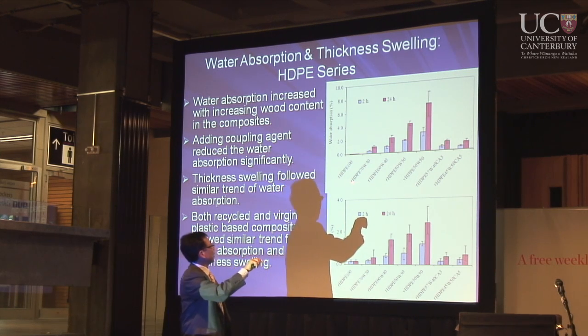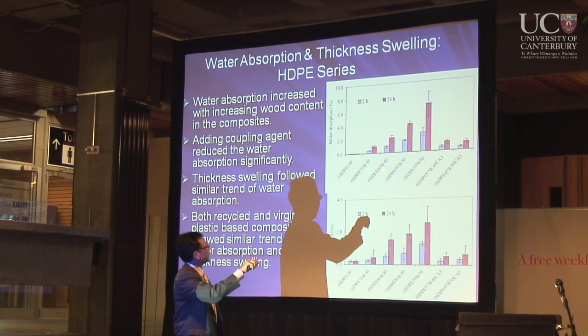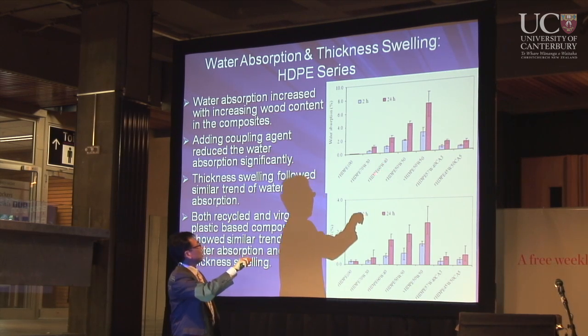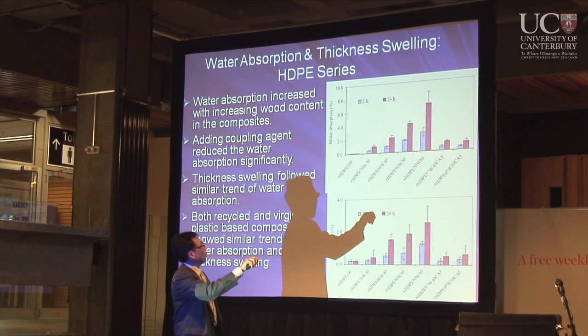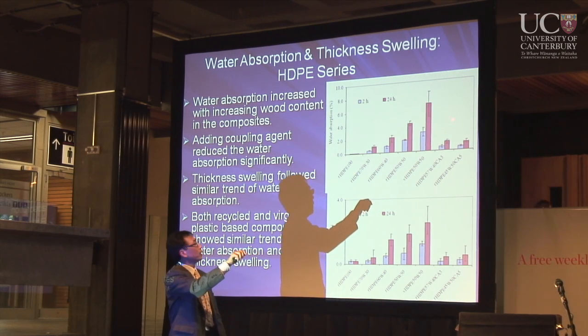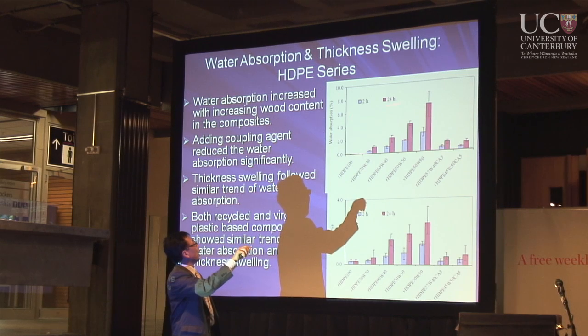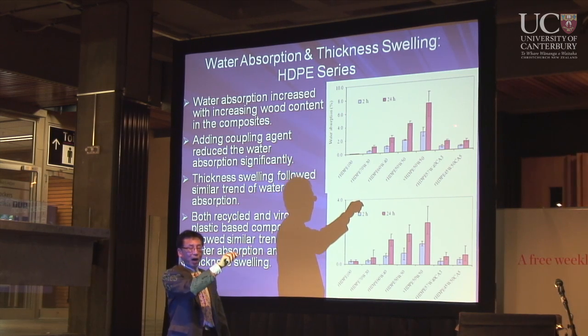And then this is recycled plastic. This is 60% plastic and 40% wood. This is 50-50. This is 2 hours, this is 24 hours. If you look at this one, this is 50-50, a lot of water is absorbed by the material after 24 hours.